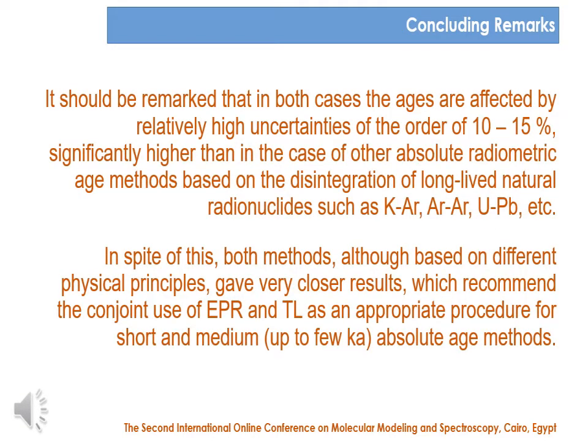As a final conclusion of this study, it should be remarked that in both cases the ages are affected by relatively high uncertainties, of the order of 10 to 15%. They are significantly higher than in the case of other absolute radiometric methods such as potassium-argon, argon-argon, and uranium-lead, all of them based on the disintegration of long-lived natural radionuclides. But in spite of this, both methods we have used, although based on different physical principles, gave very close results, which recommends the conjoint use of EPR and thermoluminescence methods as an appropriate procedure for short and medium time ages, in our case up to tens of kiloyears.